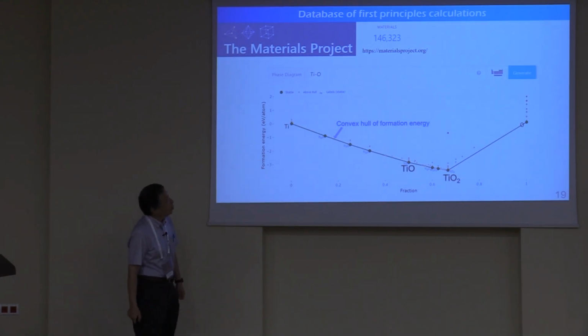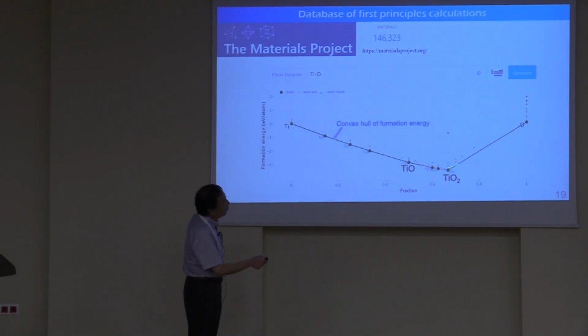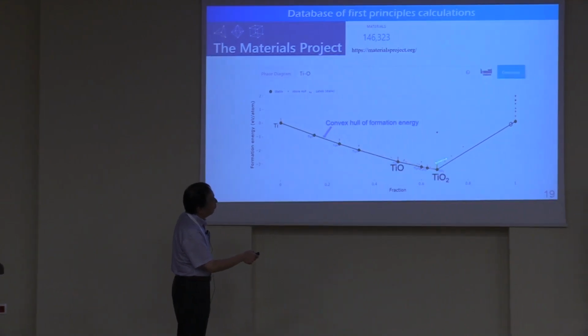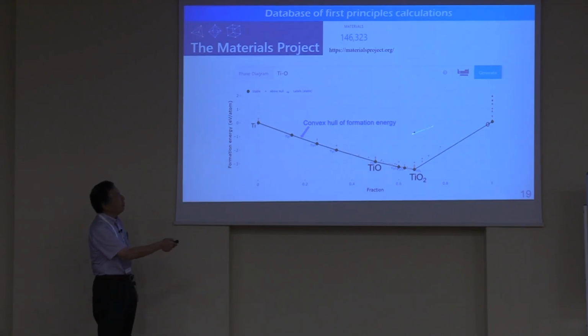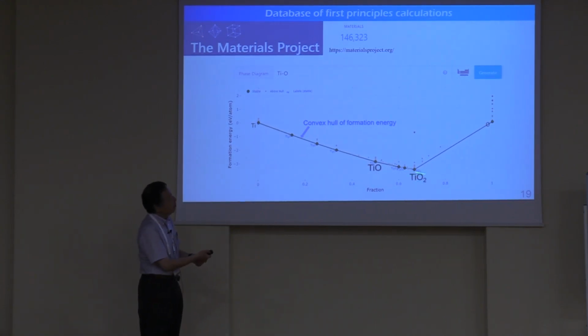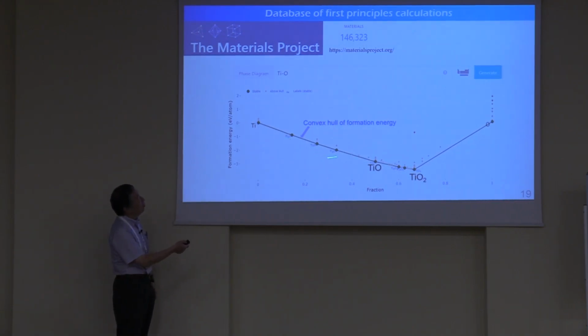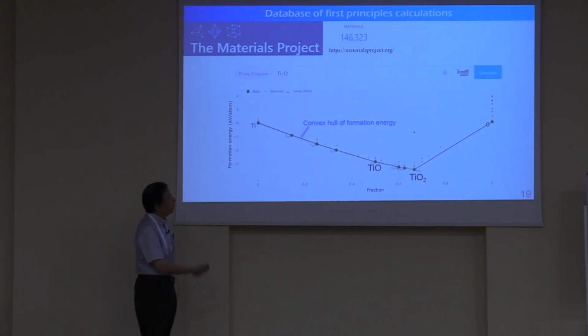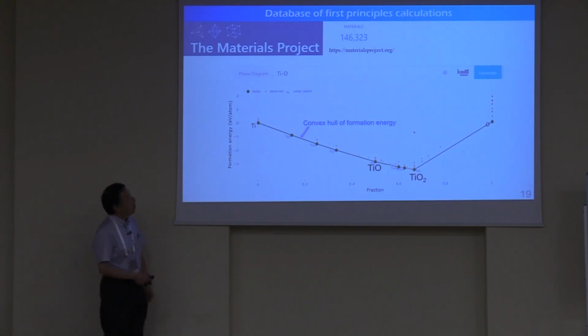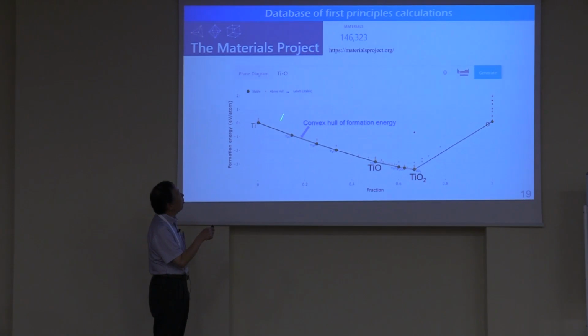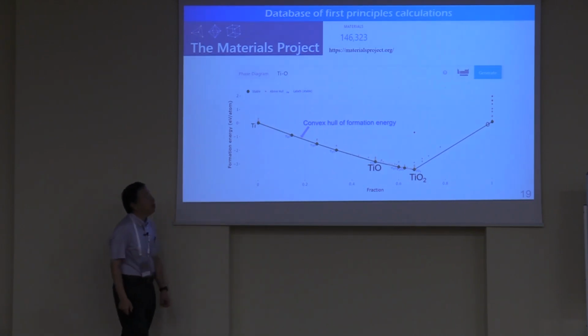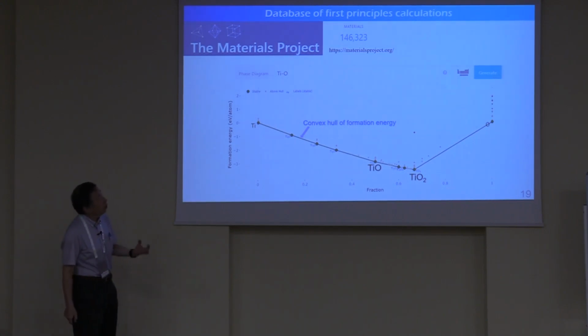Probably the pointer is very small, so it's difficult to see, but there are some other points you can see. They are the same chemistry, but different composition, or same composition but different structures. So among many different structures, one of the structures has the lowest energy, and it is located on the convex hull. It means those are thermodynamically stable. But other compositions, something like Ti8O, are not on the convex hull, so they are not stable. I will explain that also afterwards.